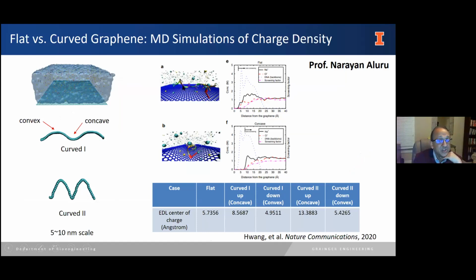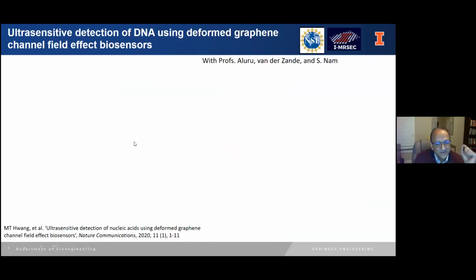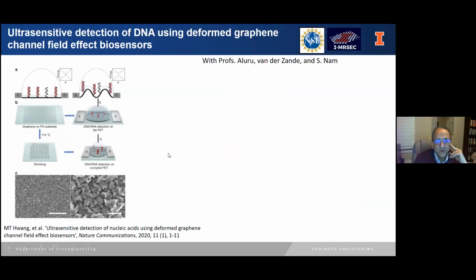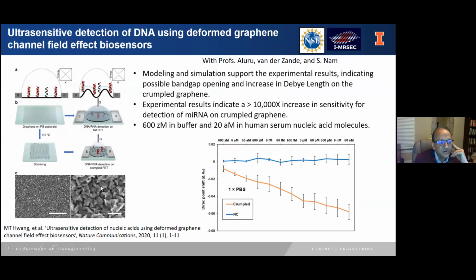So he did molecular dynamics simulation of individual molecules on graphene with ions and showed that indeed the Debye layer is different on a concave surface versus a convex surface. This was shown by the other paper also. So we then made devices, and this paper was published past year in Nature Communications. Long story short, when you have these crumpled surfaces, you get both concave and convex regions. And it turns out that the Debye layer is extended. So you get regions where the molecule is not shielded and hence it can be detected at lower numbers.